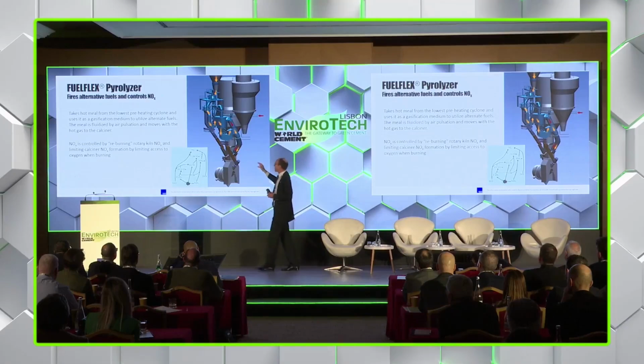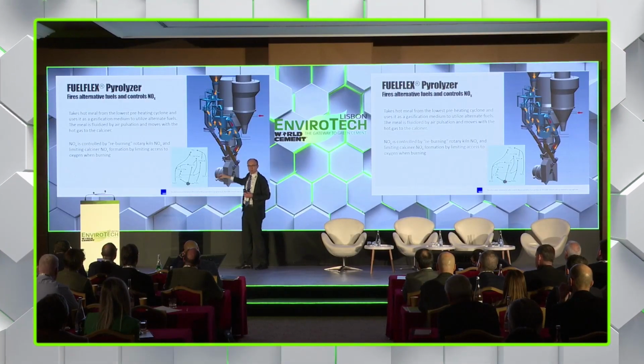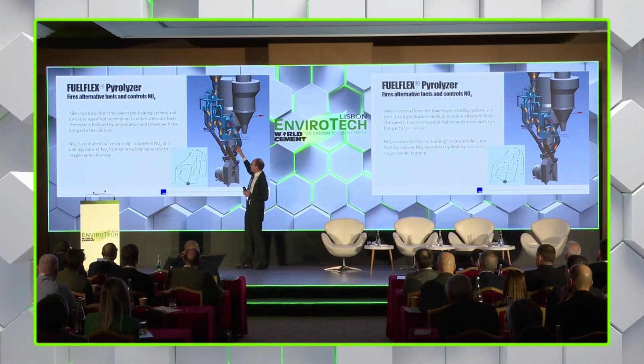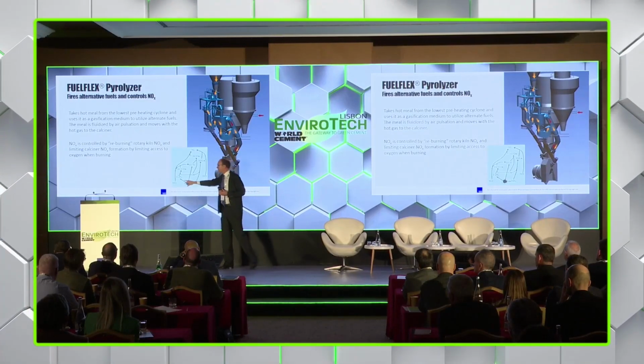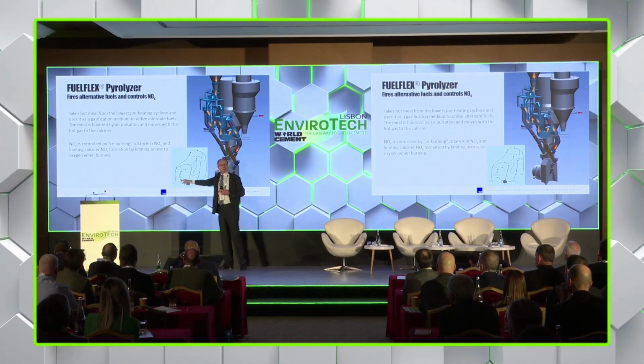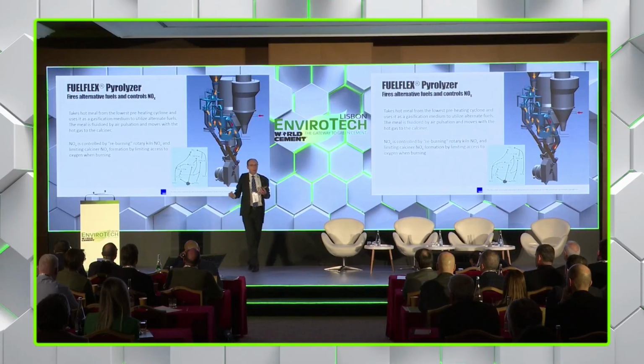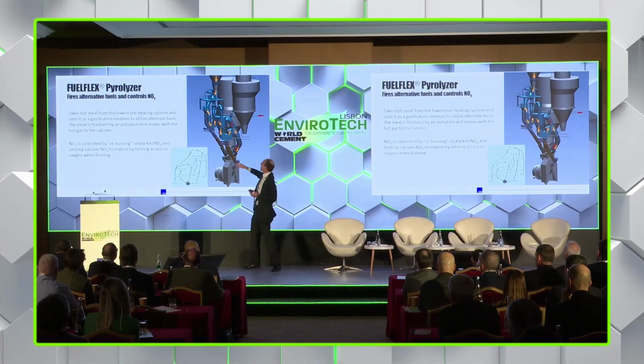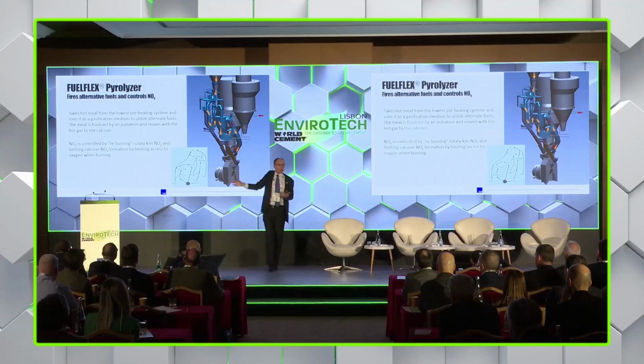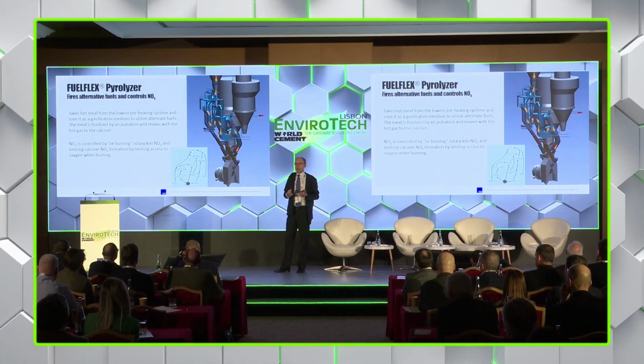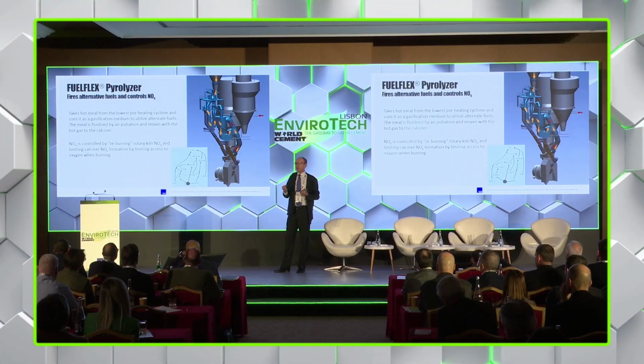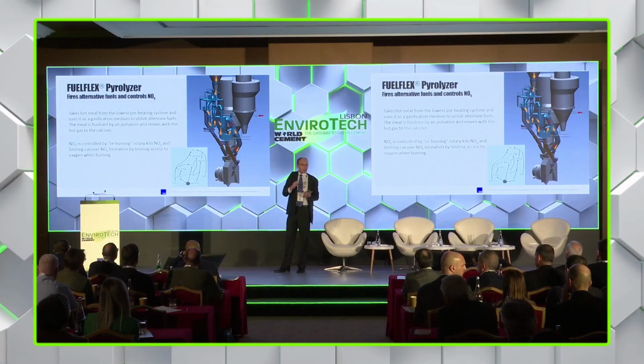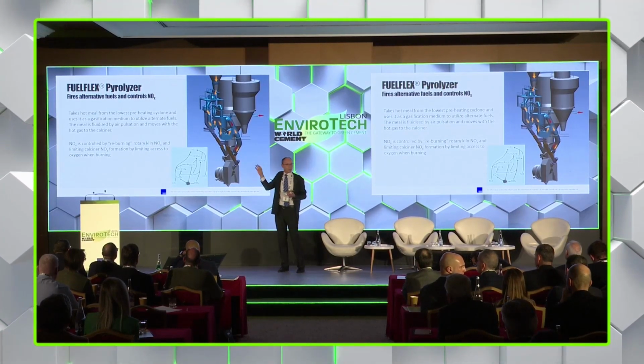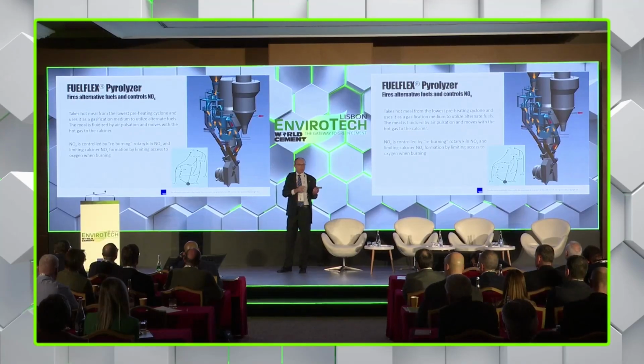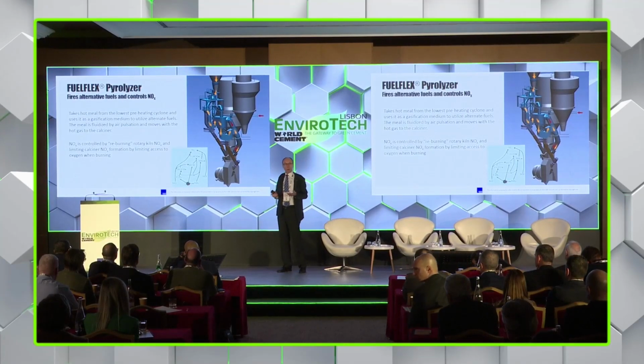The difference now is simply that this unreactive fuel has become an extremely reactive fuel stream. This fuel then meets the nitrogen oxide coming from the kiln gas down here. Because it's so reactive, it then converts the nitrogen oxide to free nitrogen, and thereby we reduce the NOx. On going further up, it meets the tertiary air, and then it burns very quickly. Because it's also now so reactive, we can get away with a much smaller calciner design, so there's no need to extend the calciner. We can use calciners designed for fossil fuels to burn these alternative fuels.